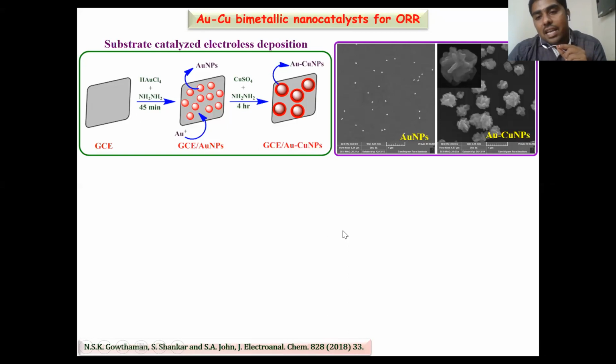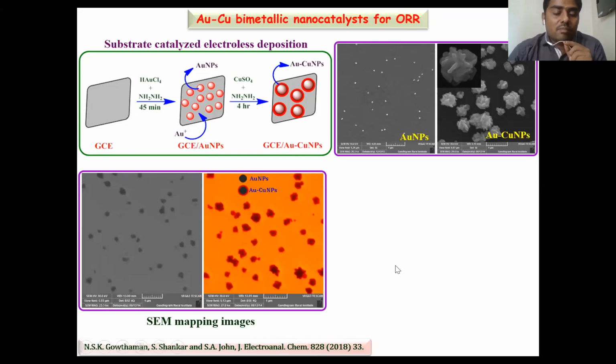And the SEM images show the gold nanoparticles as very spherical particles in the range of only 60 to 70 nanometer, and after the formation of gold copper bimetallic nanoparticles, it shows some different structures with elongated rods and flower-like structures. We also confirm the formation of gold copper in the composition with the help of SEM mapping analysis. So we use the secondary electron detector for the mapping analysis, and here the gold and copper individually show that there is a formation of gold copper bimetallic nanoparticles on the surface.